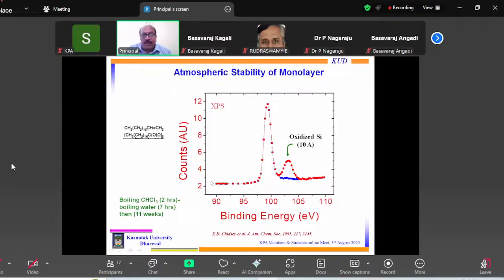What is more important is that overlapping along with this is a blue line spectrum. And these are the molecules which were bound on silicon by these groups. Then they recorded the spectrum. They don't see any oxidation. It means the passivation by organic molecules is so perfect. These molecules do not permit oxygen to come and bind or convert silicon to silicon oxide.